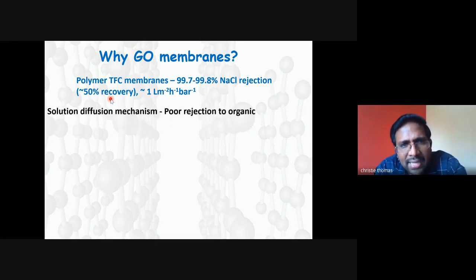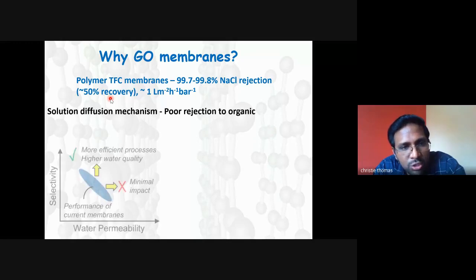This membrane works on a solution diffusion mechanism. In the graphene oxide membrane, as I told you, the selectivity is defined by ion dehydration, and basically this is a geometric rejection. In GO membranes, it's basically a size exclusion mechanism. In polymer TFC membranes, it's a solution diffusion mechanism. It has poor rejection of some molecules, organic molecules. It is very good at rejecting salt, but it has very poor rejection of organic molecules.